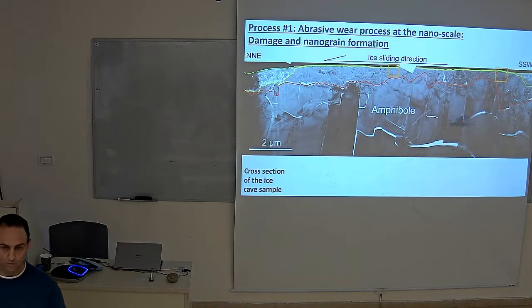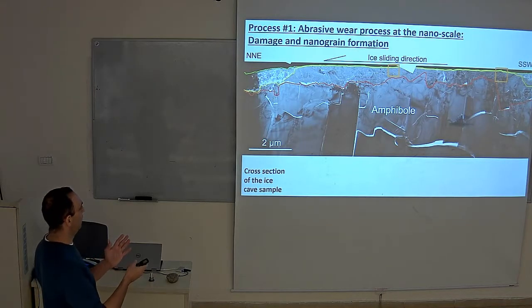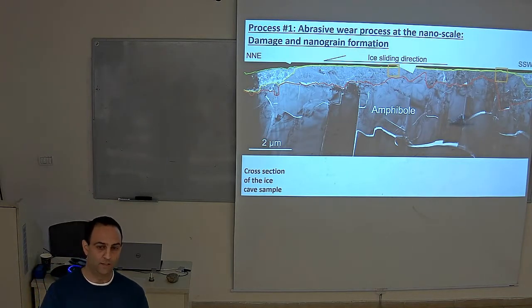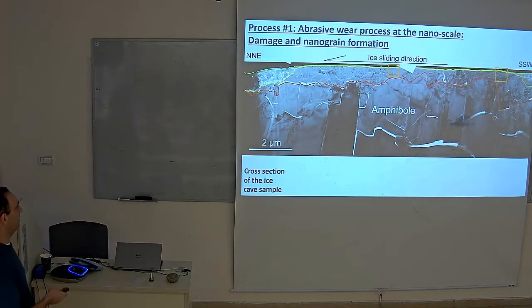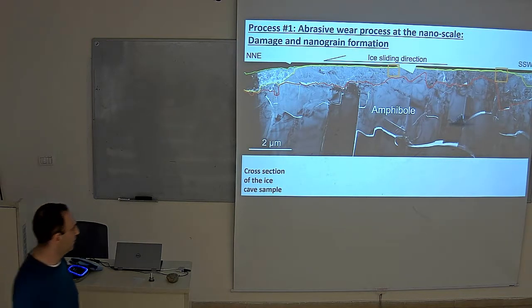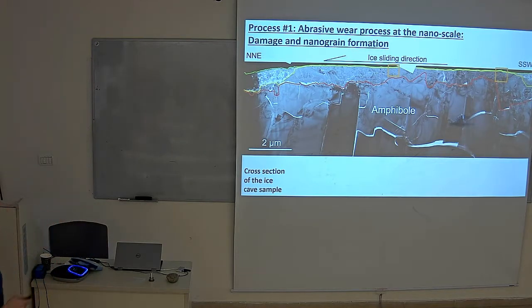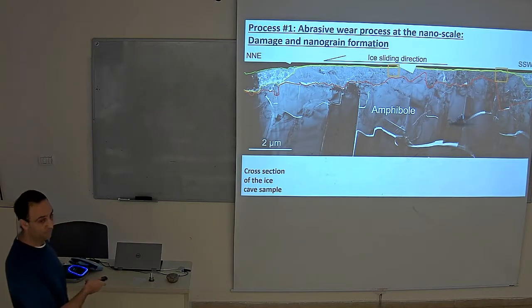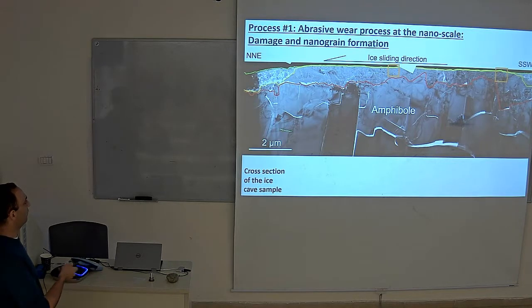I collected the sample, about a centimeter in size, and then I went to the lab, happy to research, and using focused ion beam, I cut samples that are similar to slides that we use in cross-section in optical microscope. However, they are much smaller. The size is about 10 to 15 microns, and the thickness is about 100 nanometers. And then we look at them with transmission electron microscopy. So this is a bright field image, which means that the voids are in white, lighter colors. And this is an amphibole crystal of the original bedrock. The green line is the polished surface, the outer, and this is inner.